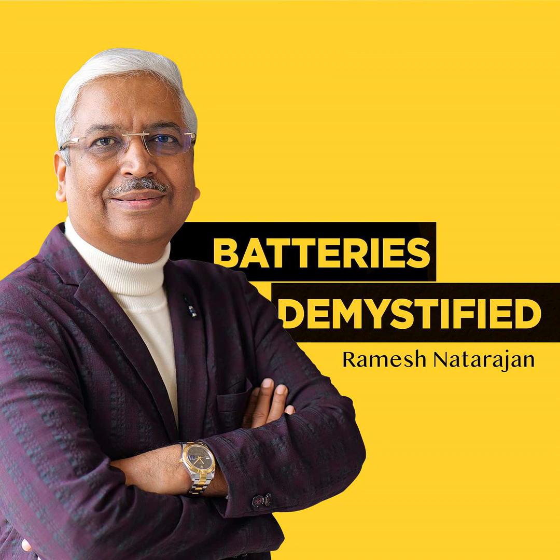It's got a large number of very fine polymer lengths extending from the cellulose backbone. What that does is it disperses readily in water, and those entangle with one another, adding different mechanical properties to the final product. So when we put this into our negative electrodes, we did mechanical testing and saw that it was 30% stronger than the control electrode that just had Vanisperse A in it. It had no negative performance impacts or rheological impacts to making that battery. Since you say it's cellulose, it must be having some effect like glue. Very much. Yep. Very much like glue.